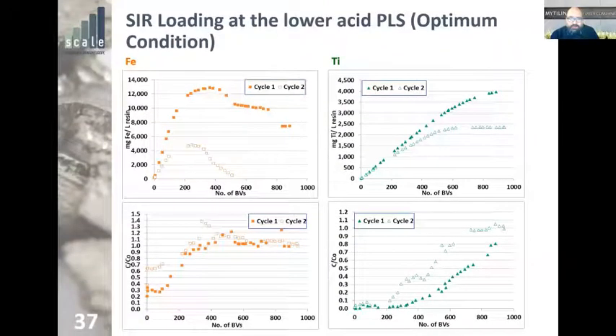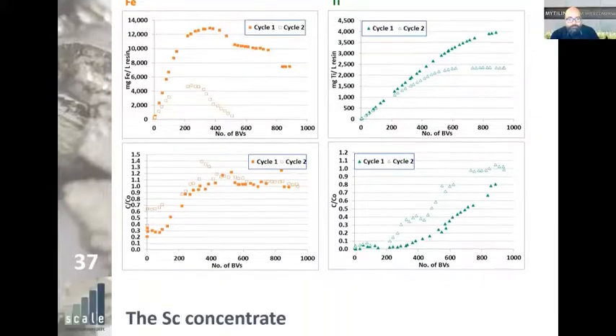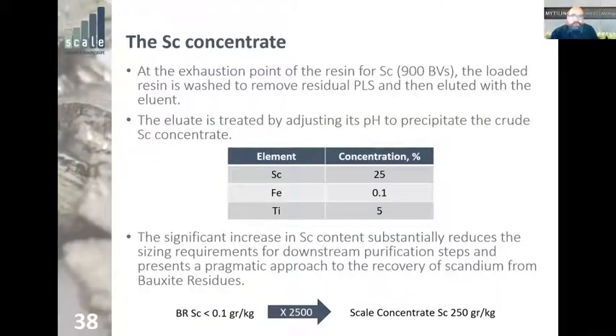These are the other elements, iron and titanium, in similar graphs. You can see that titanium did not go that high. It's just 4,000 milligrams per liter, and iron was 12,000 milligrams per liter. And in the second cycle, both elements were collected less. So after we loaded the resin up to the exhaustion point, about 900 bed volumes, the resin was washed and eluted in order to get a scandium pregnant solution, which was precipitated into a crude scandium concentrate.